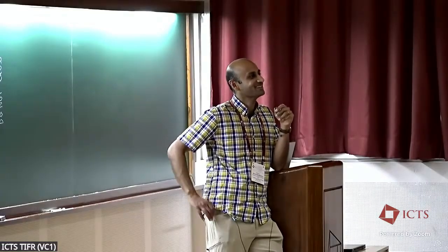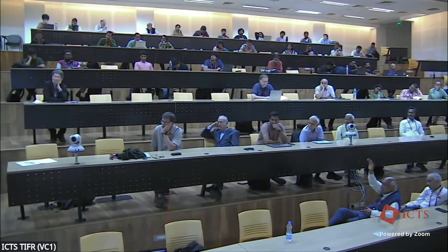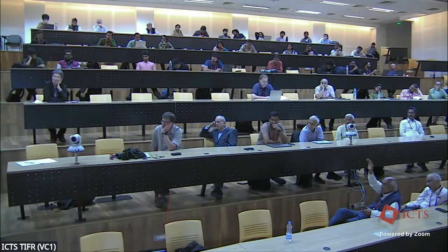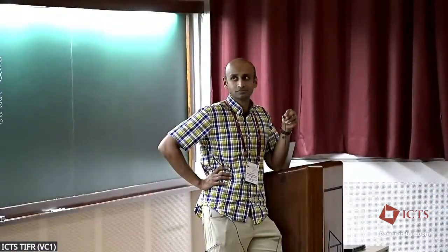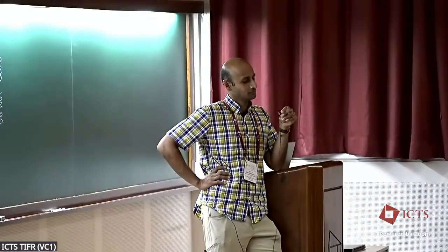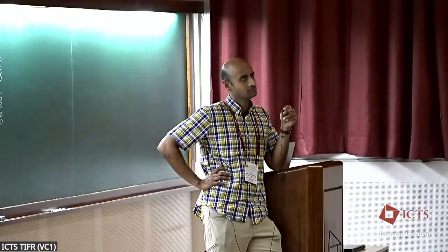I want to add one thing there. This Higgs mode is very close to the 2 delta pair breaking energy scale in a BCS superconductor, a clean superconductor. But if you put in disorder, even in a BCS superconductor, the gap scale remains unchanged and the Higgs mode moves down in energy. So there's a separation between these two. So you should be able to see the Higgs mode more cleanly, and that would be, I think, useful.